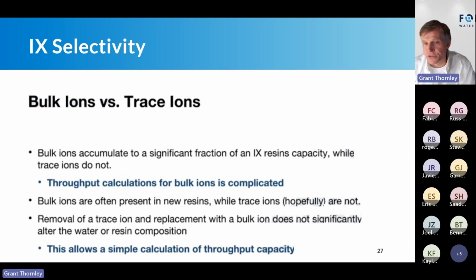So bulk ions versus trace ions. Bulk ions accumulate to a significant fraction. Oh, it's 10:52. I apologize. A lot to get through. Bulk ions accumulate to a significant fraction of the ion exchange resin capacities, whereas trace ions don't. So throughput calculations for bulk ions, meaning we're very, very high, gets complicated because of the interactions. Trace removal is less complicated and can be modeled out.